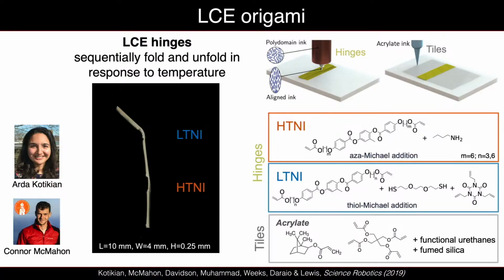And then we also connected these by 3D printing to rigid tiles. So these LCE features, which are printed in such a way that we have a mountain or a valley fold, are connecting tiles that we also print out of a stiff acrylate ink. So what you're going to see here is a movie I'm going to play. Each one of these little features here is a bilayer of this material. And we're going to start heating this up. And you should see this feature fold first because it has a lower TNI, and then this one.